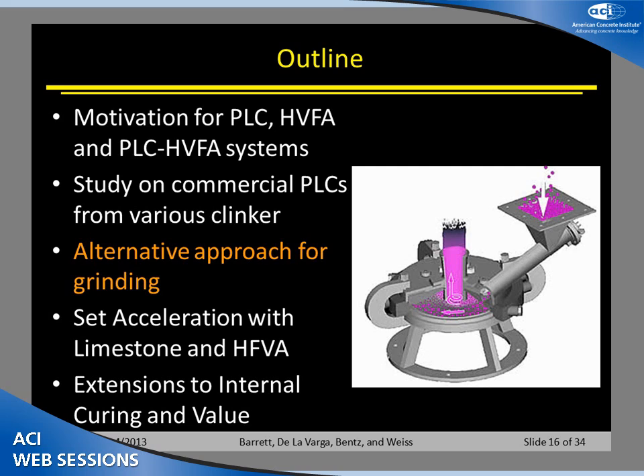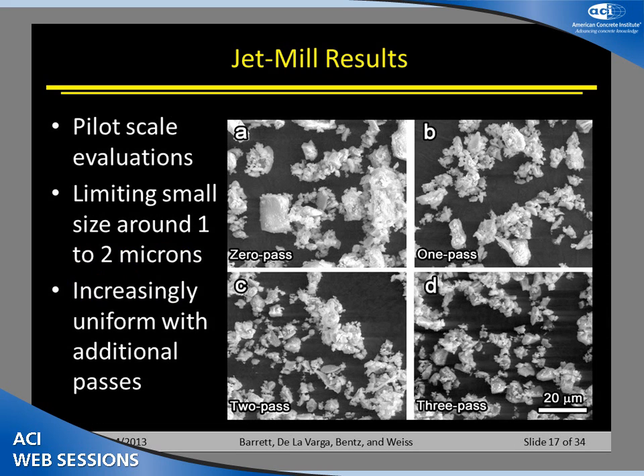One of the things that we've actually been looking at is the approach of using this device over here, called the jet mill. The basic idea is we drop the material in and we essentially get it moving in an airstream and we collide it with itself. When it collides with itself, it breaks up into smaller particles. This is a technology that we've been looking at to see if we can reactivate some materials that are out there or make very, very fine particles that could be very useful.